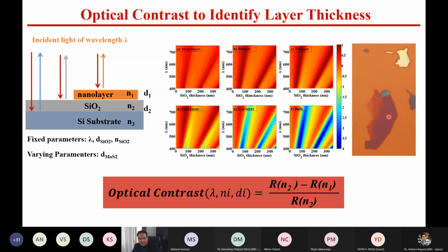So what we do is we calculate the optical contrast as a function of the silicon oxide thickness. The y-axis is the lambda of the light, and the x-axis is the silicon oxide thickness. So what is the right thickness of the silicon oxide on the silicon substrate, so that you are able to see the nano layer very clearly on top of it? We have done these simulations and found that there are some specific regions where the optical contrast is higher for the monolayer, and you need to choose the right kind of silicon oxide layer to find out where the monolayer is.